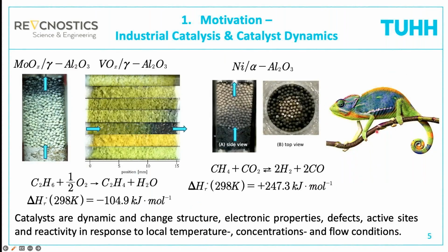And then there is another thing that makes our life quite complicated, and this is that catalysts change dynamically in the reactor. I have brought you some pictures from our lab where you see catalysts under reaction conditions. On the left side, you see, for example, a molybdenum oxide catalyst supported on gamma alumina. And the reaction we are doing here is the oxidative dehydrogenation of ethane to ethylene. The flow is from bottom to top. And you see when the feed enters the reactor, the catalyst is colorless, which means molybdenum is in an oxidation state of +6. And then when the oxygen is consumed, you see that the catalyst turns dark blue or violet, almost black in some cases. And this is molybdenum in an oxidation state of +4. So you see how the oxidation state changes.